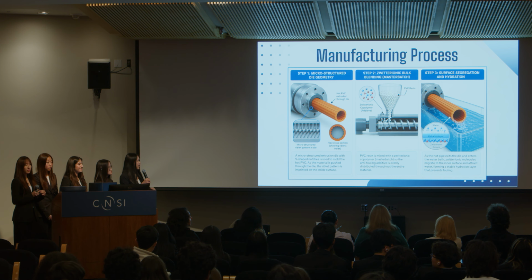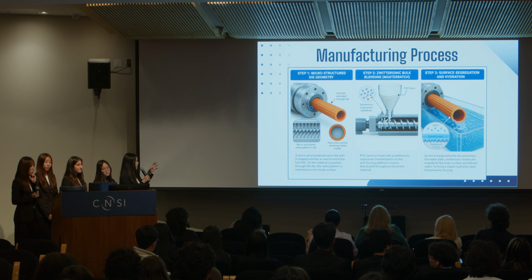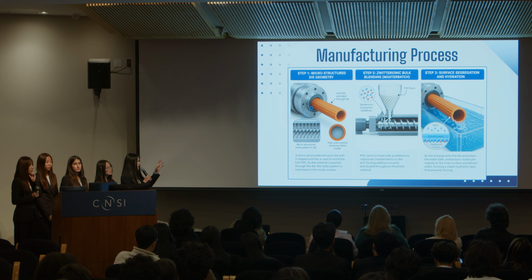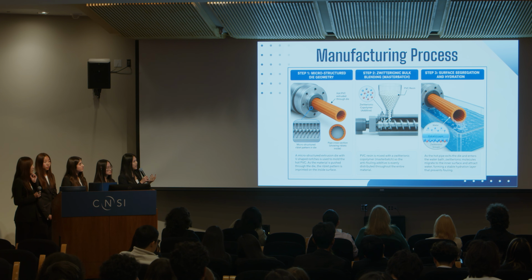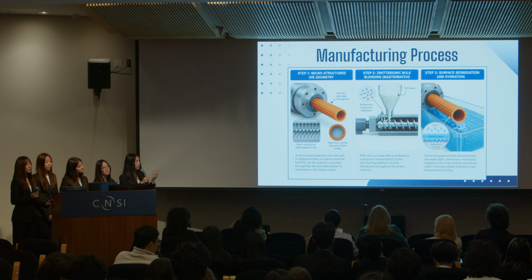Okay, so I'll start with the Zwitterions first, just because that's incorporated into the PVC. We would first create a master batch blend, combining the Zwitterions with the PVC. Then, to create the shark riblet structure, we undergo a process called microstructure geometry extrusion. We take this hot PVC with the Zwitterions embedded into it and put it through an extrusion mold, which embeds these riblets in the interior of the pipe. After that, we perform surface segregation.